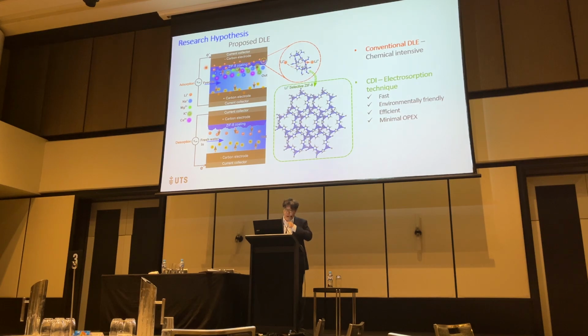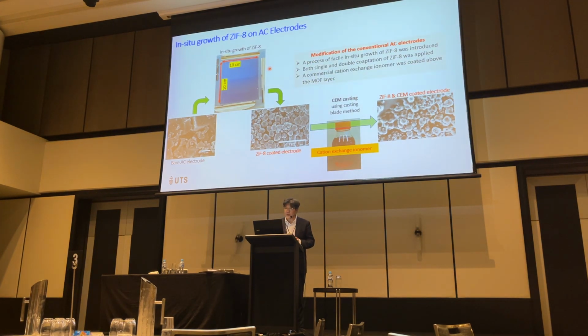You can see that we have CDI. Then we try to coat it with ZIF, because the ZIF pore size is very similar to lithium, so that we can selectively utilize the ZIF gate. Then just lithium passes through, and we can collect only lithium from this CDI electrode. So that's our result comparison.